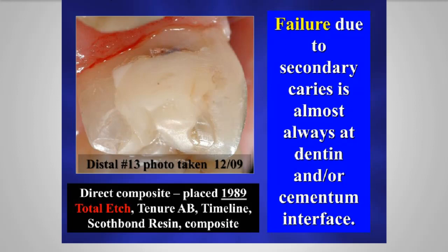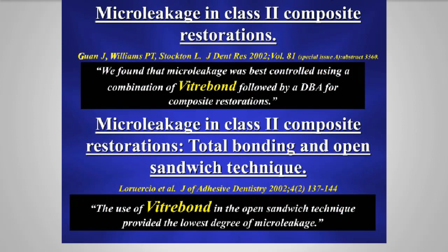Years ago, I set out to write a paper, and the idea behind the paper that I was going to write was to show that the best way to attenuate micro-leakage was to use a dentin bonding agent followed by a flowable composite. And after I did a literature search and some of my own research, what I found was kind of the opposite of what I was looking for. I found that study after study, it was resin-modified glass ionomer liners that did better in terms of micro-leakage than flowable dentin bonding agent combinations. And as a result of that, I kind of changed my protocol.